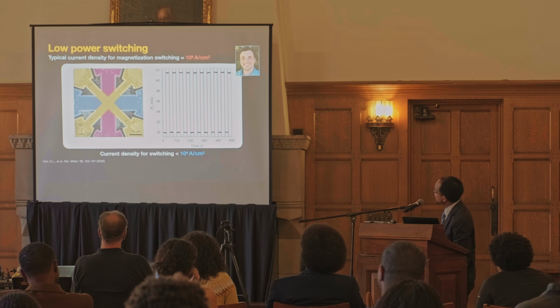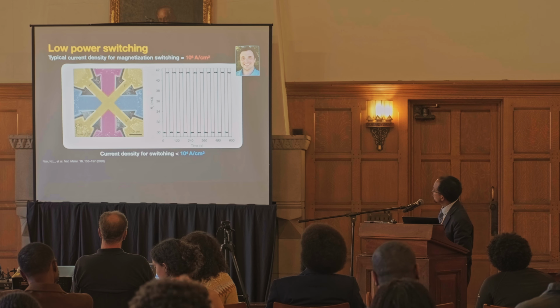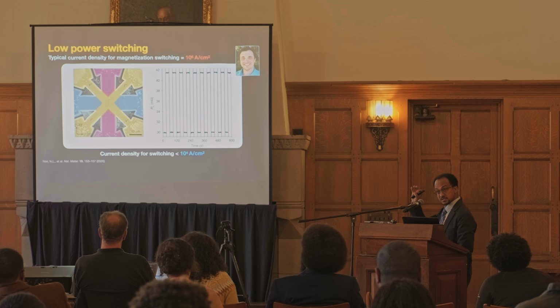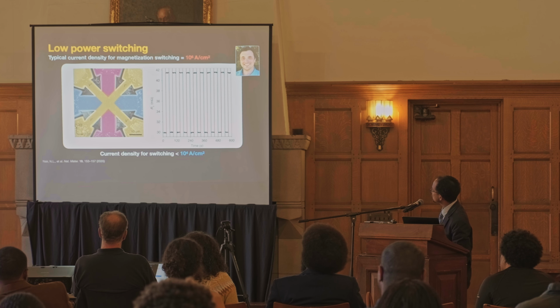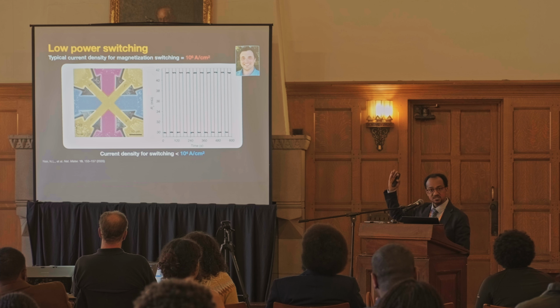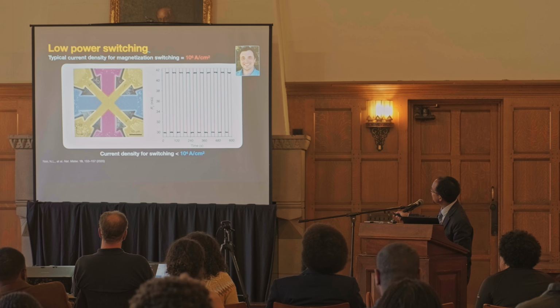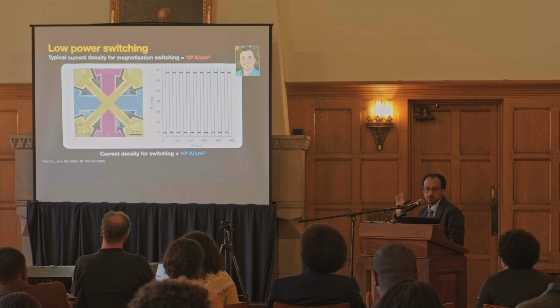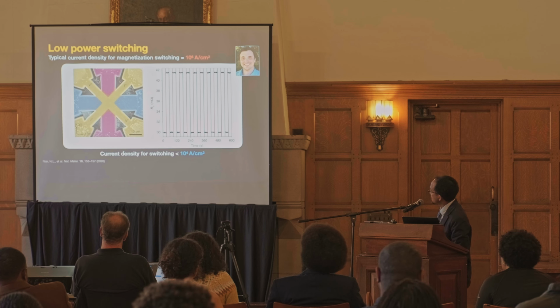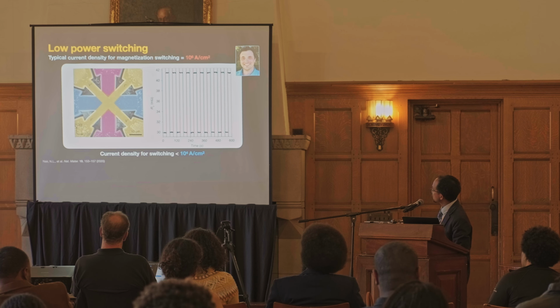And the reason this is important, this is my last slide, is that for this family of materials, a collaborator of mine, James Analytis, also at Berkeley in the physics department, and I are working together because we've found that there is one of these materials, the same type of structure I showed you before, that allows extraordinarily low switching between two states. Typically, when you want to switch the magnetic properties of a material, you need about 1 million amps per square centimeter in basically all conventional magnetic systems. These materials that I've shown you require 2 orders of magnitude lower current to switch. And it's very sharp and very reproducible. So we're trying to understand, one, where does this come from? What's the origin of this, and how can we leverage that moving forward?